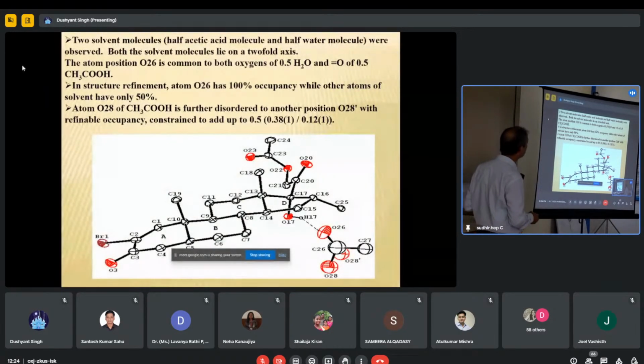It took me months to resolve this. So now what happened? This oxygen has 1 occupancy. All other atoms of the acetic acid molecules have 50% occupancy. No, it is not only the oxygen of acetic acid, 50% occupancy of water solvent is also present. So this oxygen is 50% belonging to the acetic acid, 50% belonging to the water solvent.